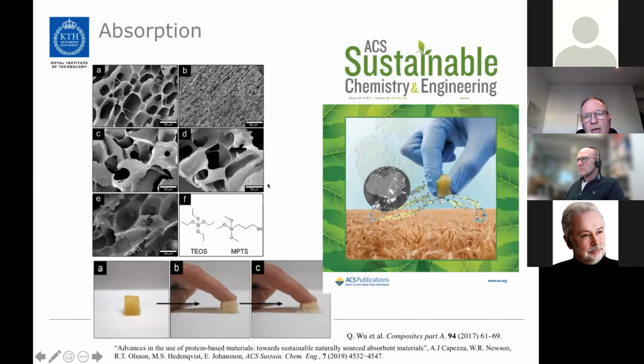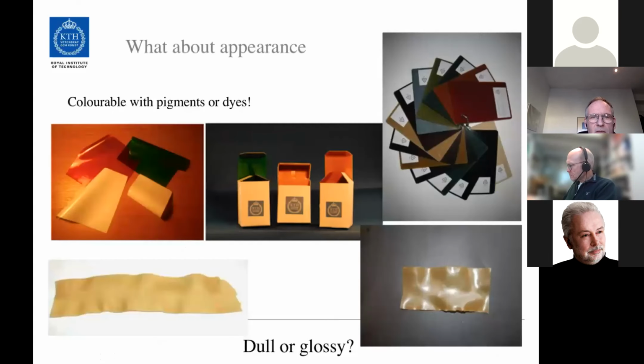With these foams, we have also been developing what we call super absorbent polymers. They are not super absorbing to the extent of the commercially available super absorbents, but they can swell quite a lot and take up 40 to 50 times their own weight in water, for example. So we're exploring this material for applications in super absorbing applications.